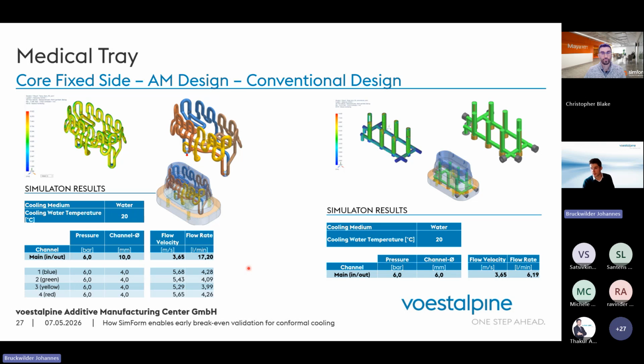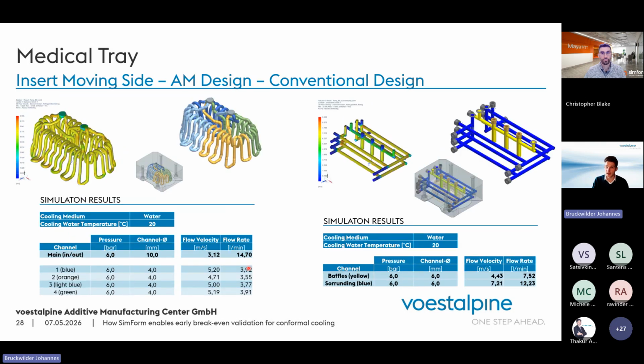That's a huge improvement, and not just for the fixed side, but also, of course, for the moving side. Here we have the buffer and the surrounding channel. You see them here. Together, you get 19 liters per minute. And what's important here with the conformal cooling, we have a lower flow rate, but we are in the areas where the heat needs to be extracted. And that's very important.